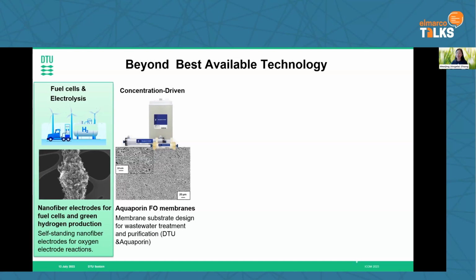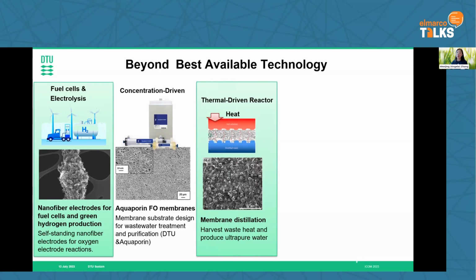And we also realize that actually there is a tremendous amount of waste heat nowadays. And that's why we also focus on thermal-driven water purification. Here is membrane distillation, and they use waste heat as a driving force to produce ultra-pure water. Often the most challenging part is the membrane itself. So it needs to be hydrophobic and also anti-fouling. So we use electrospinning to create special shapes to boost the hydrophobicity.